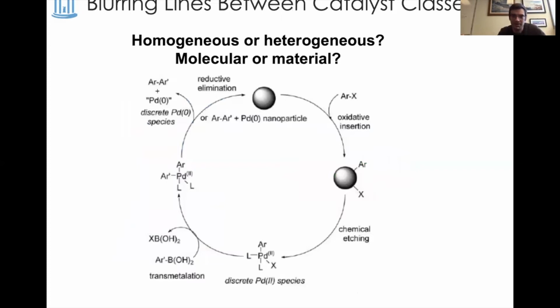So I'll give a couple other examples of blurring lines between catalyst classes. This is an example I love because of my own background in molecular catalysis and frequent concerns that a molecular catalyst is simply decomposing into a highly active nanoparticle or metallic catalyst. Here's an example of a palladium nanoparticle that's used as the catalyst for a Suzuki cross-coupling reaction. And mechanistic studies showed that the active catalyst itself, after an oxidative addition of the aryl halide, undergoes an etching process to generate a discrete, well-defined molecular palladium species that undergoes the transmetallation and reductive elimination steps.